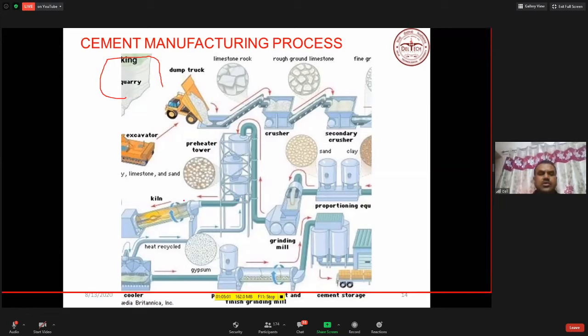Now it is going into the kiln, and here the temperature rises up to 1500 degrees centigrade, so the clinker is formed. Then this material comes down here, and from here the clinker moves like this. Here the gypsum container is there, where you put the gypsum. So gypsum is added to this material, and this material comes to this silo.